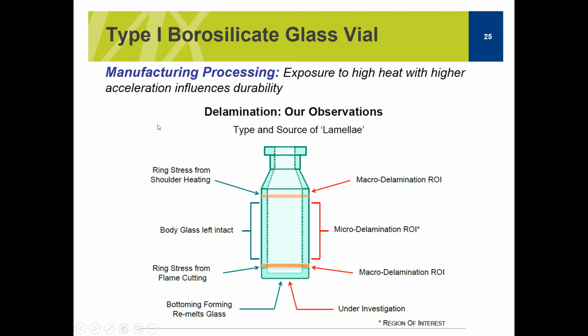Again, Gerresheimer, what they did is they took a look at the vial, and they looked at which regions are more vulnerable to delamination. And what they found out is that a region that has been in contact with high heat is a region that causes delamination. So right here on the bottom, and also right here on the neck. So these two cause macro, meaning large amounts or large pieces of laminate, and here, micro, so not a lot of stuff happens here.